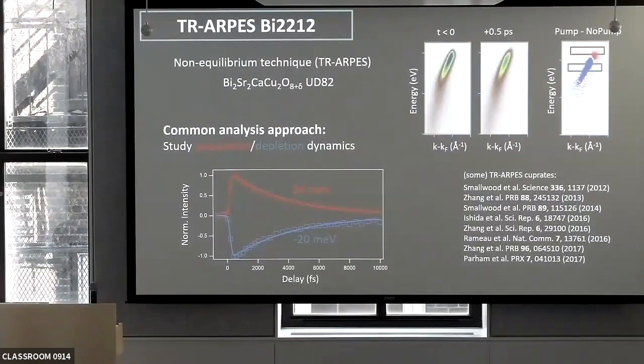And as I highlighted, one can do an experiment where, at some negative time, usually meaning before the pump has come in, you see a band dispersing all the way to the chemical potential. And after some delay, if you pump it, there is a change in population around that peak. Usually you show difference plots, so the pump minus the no-pump signal, and then you can see a depletion of signal below EF and an increase of signal above EF. Generally you will see traces like this, showing the evolution of that signal as the pump arrives: increase above EF, depletion below EF.